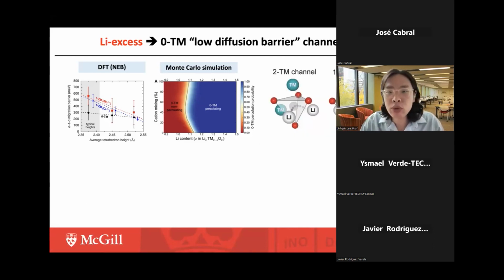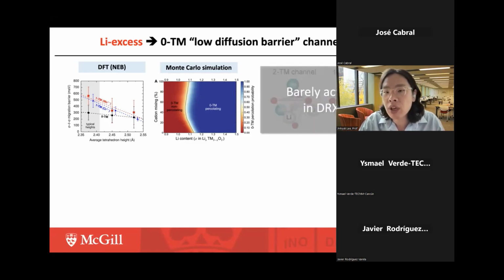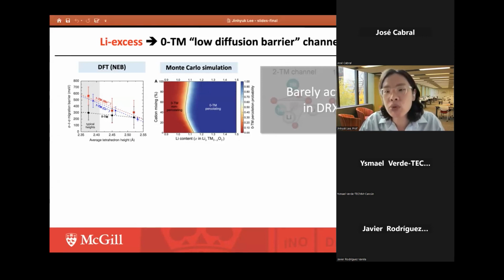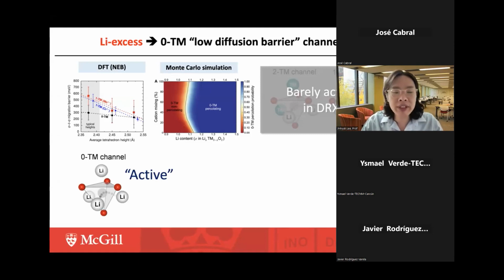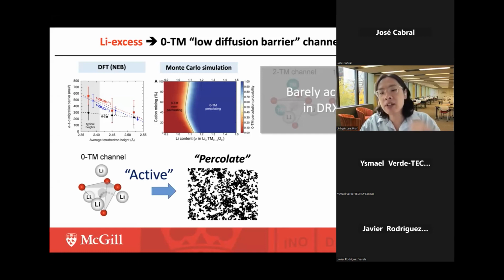So here you see the 2TM channel, with 2 transition metals, and the 1TM channel, with 1 transition metal, and 0TM channel means there's no transition metal around this diffusion pathway. What we found from the DFT calculation is that both the 2TM and 1TM channels are barely active in the DRX structure, but we have a channel called 0TM channel, which allows the lithium to jump to the neighboring lithium site. If the population of 0TM channels is large enough that they start forming a giant network within the disordered rocksalt structure, then because the 0TM channel is active, if they percolate, lithium diffusion can continue to take place through this active 0TM channel uninterrupted by other inactive channels, so that the diffusion in the DRX structure can be fast.